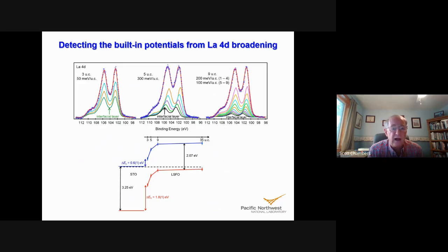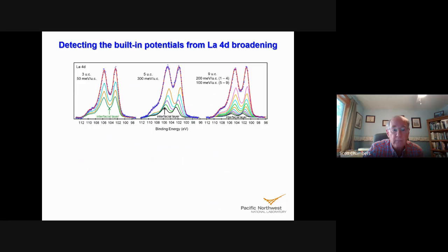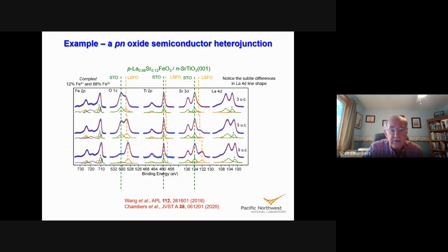Right, that's a great question. I didn't show it, but if you look at the strontium 3d spectra, and you strip away the component that is from the LSFO, and then compare the line shapes for the different thicknesses of LSFO on there, what you find is that line shape is identical to what you measure for flat band STO. So that's how we know there's no band bending in the STO. Okay.